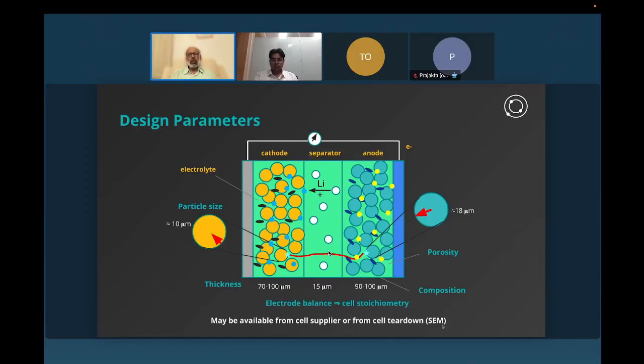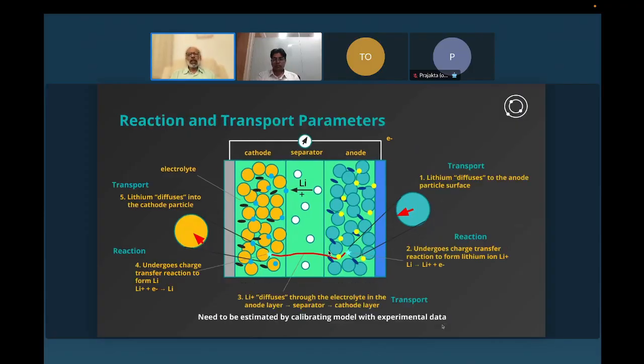So these are some of the inputs, and then going to the next slide, which is the focus of the presentation today, is the reaction and transport parameters. We talked about transport and we talked about diffusion. That's a transport process. And the diffusivity of the particle, diffusivity on the anode, is an example of a transport parameter. And similarly, we talked about reactions, and the reaction constant is a reaction parameter. So we have a set of transport parameters which consists of diffusion coefficients and a set of reaction parameters, which are the reaction rate constants.